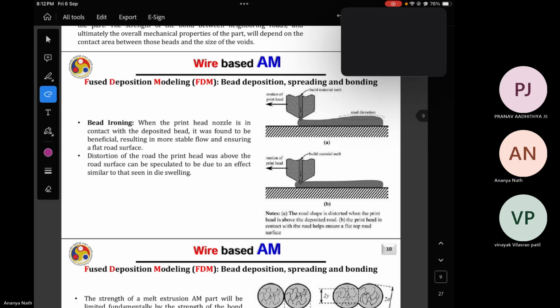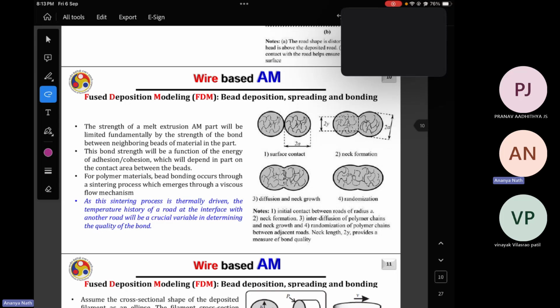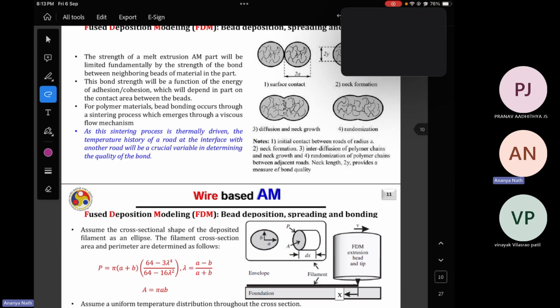Apart from that, even if you are depositing in optimal condition, if your layer thickness is very high, then you'll get some distortion over your bead. So in that case, the nozzle will not deposit the wire from far away. Rather, the nozzle will deposit in such a way that when the bead is deposited, the nozzle will touch the upper surface of the bead. So if it touches the bead, then it will iron the bead's upper surface, and you'll get a flat bead, so your surface roughness will be lesser. So this bead ironing is one technique where the nozzle touches the bead and deposits it. Then there is the neck formation and final growth and fusion of the beads.